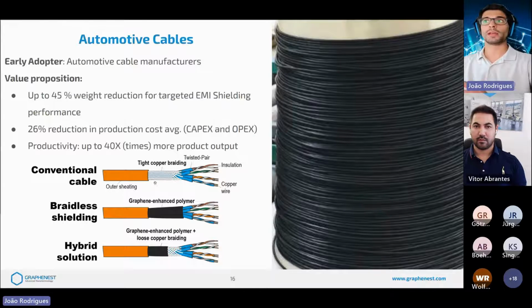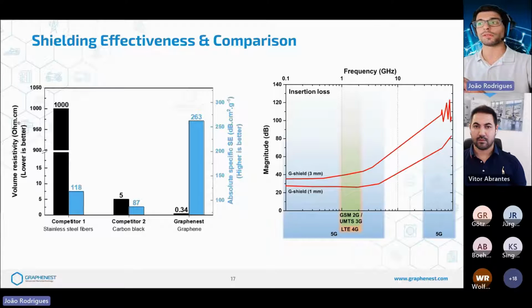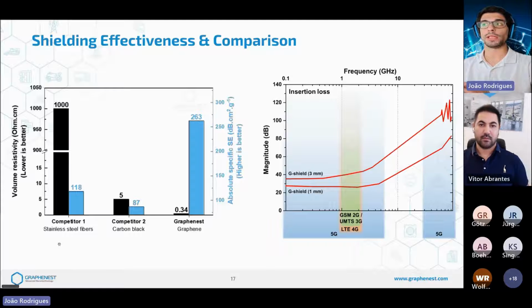And just to conclude, I just want to show a little bit of data for those of you that are more interested in the technical side. I have here some data about the shielding effectiveness of our product, and also we compare it with some competitors. You can see here on the left figure, competitor one uses stainless steel fibers, which are heavyweight, and sometimes they are difficult to integrate into a polymer without degrading the mechanical properties. And competitor 2 uses carbon black, which is tricky to disperse sometimes, and also it is difficult to achieve the proper electrical properties that are required for EMI shielding.